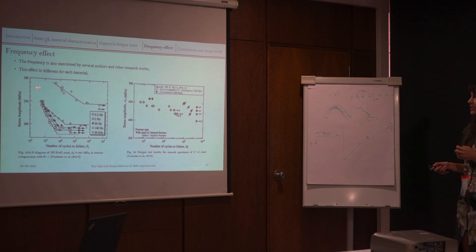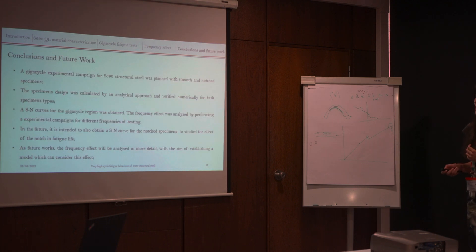So you can see here for this work on low carbon steel that we can observe a huge effect of the frequency, and for this case, that is for another steel, the effect is not so huge. But you can also see here for higher frequencies the curve is going to be a bit upper than for lower frequencies. We expect in the future to be able to model this frequency effect, or at least try to apply or develop a model that can account for this. We also expect to obtain an S-N curve for the notch effect and to quantify this notch effect.